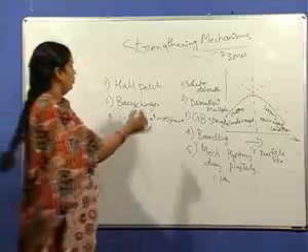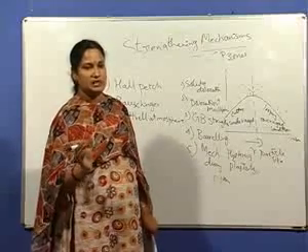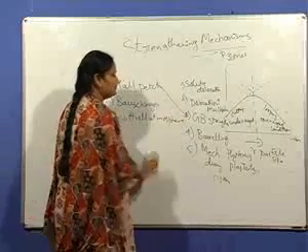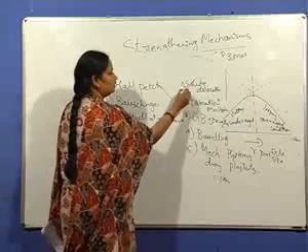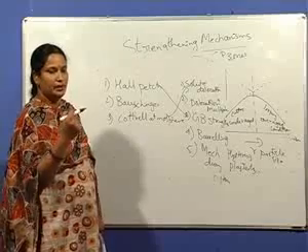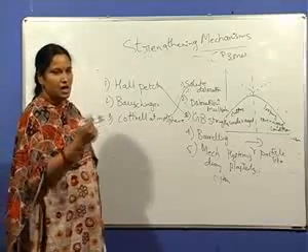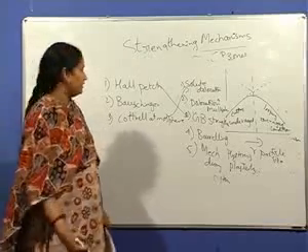So from this you can easily see, the Hall-Petch relation is related to grain boundary strengthening. Yield stress is inversely proportional to the square root of the grain diameter. So Hall-Petch is matched with 3. Cottrell atmosphere is solute dislocation interaction. Interstitial solute atoms occupy the positions below the edge dislocation and they form Cottrell atmospheres.